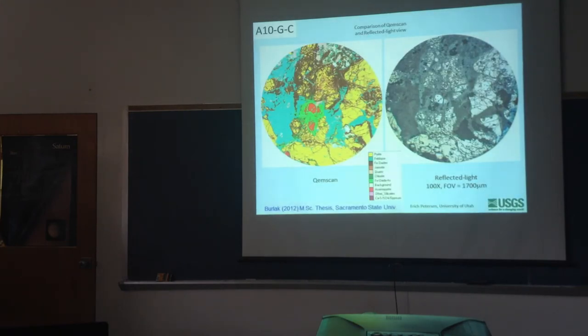And so here's, for example, what this polished section looked like in reflected light. And when we look at a QEM scan image where we've trained it to identify low arsenic hydroxides and higher arsenic iron oxides, the low ones are in brown, and the high arsenic ones are in green, arsenopyrite in red, and pyrite in yellow. You can see that the high arsenic iron oxides are right in this area around the arsenopyrite grain, and the brown gunky stuff is all out here in the pyrite. So it would be virtually impossible to tell that with the naked eye, but here we have a tool you can use to map this out.